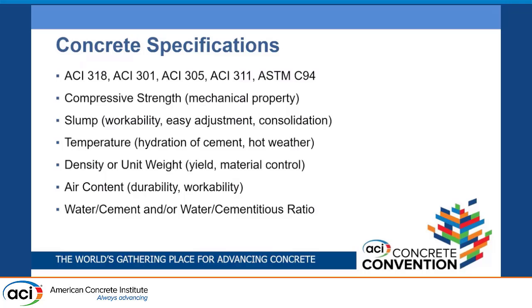Part of the concrete specifications, and this is very general, we can have guides from the ACI 318, the 301, 305, 311, ASTM C94, where on the specification, we should have the compressive strength requirements, slump, workability, that can be easy to adjust, easy to consolidate, temperature. In our case in Puerto Rico, we are classified as hot weather concrete. So the hydration of the cement and the condition of the temperatures and the admixtures that we use for that delay in the hydration, those retarders, are very, very important.